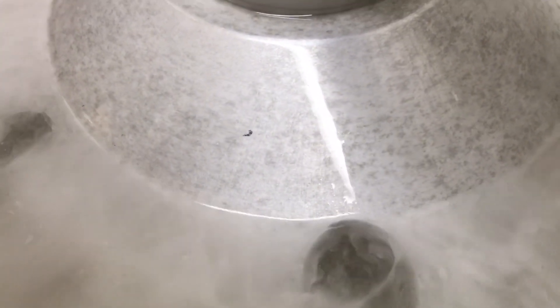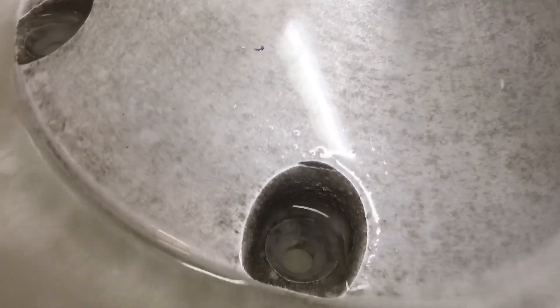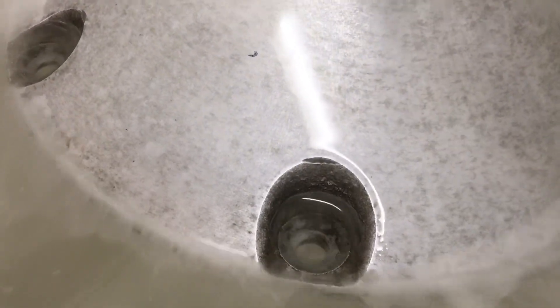The trick here is that you only want to peel off or etch off so much of the aluminum oxide so that all these spots go away. In fact, what happens when you have this solution etching here is that you form something called sodium aluminate at the surface of the aluminum. So it will never become shiny like the true aluminum metal in itself unless you polish it. But we will cover this entire piece now with formed sodium aluminate while we're dissolving the aluminum oxide so that we have an even appearance over the entire piece.